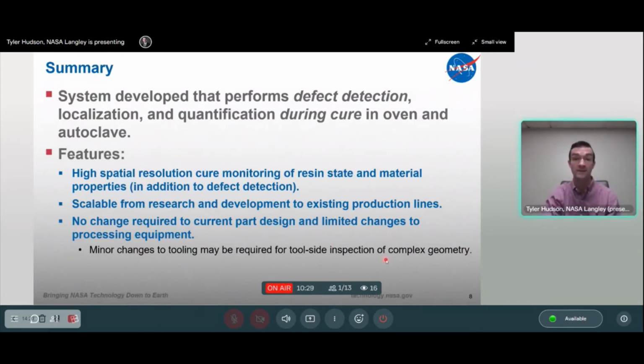And so in addition to defect detection, it also features very high spatial resolution cure monitoring of resin state. So you can determine whether your resin is liquid, rubbery, or solid. You can pick up things like viscosity, degree of cure, glass transition temperature, all on a very, very small spatial resolution. So each pixel is like 1 millimeter by 1 millimeter in our setup, and you can do this over large areas of your structure.